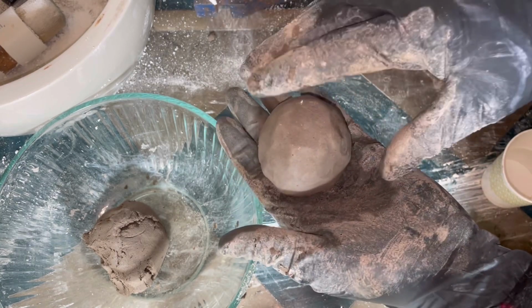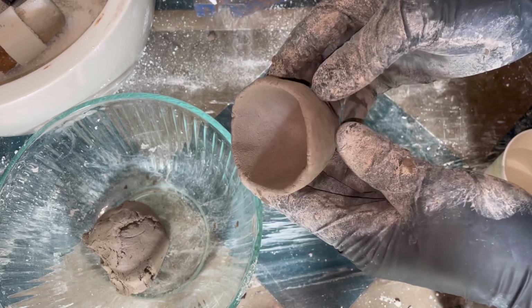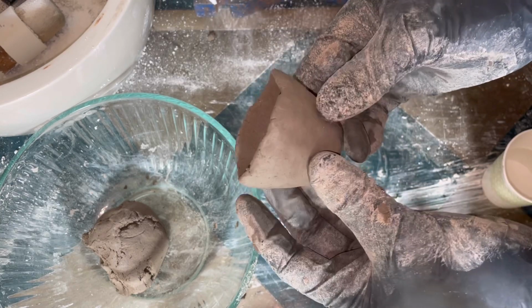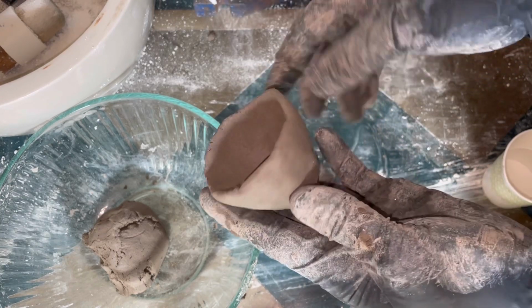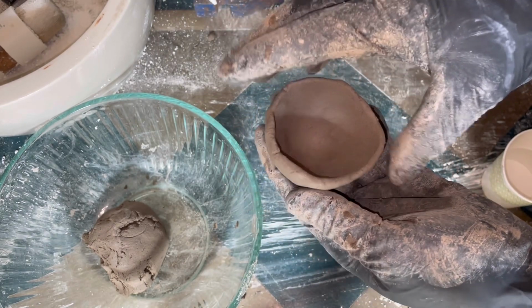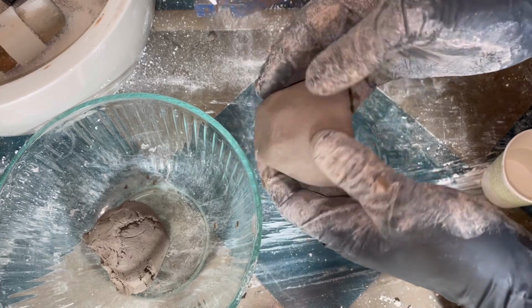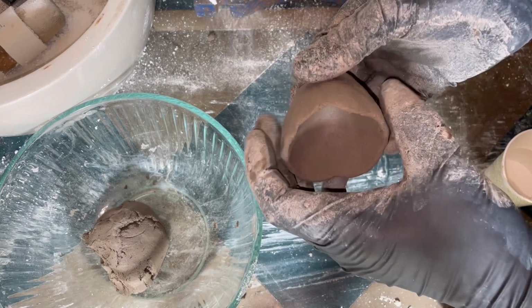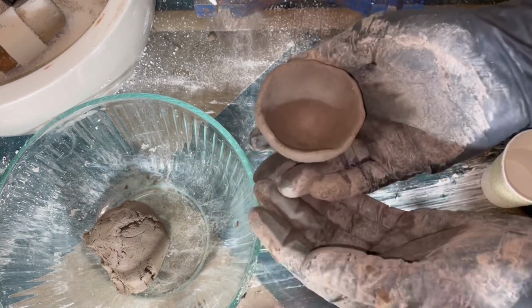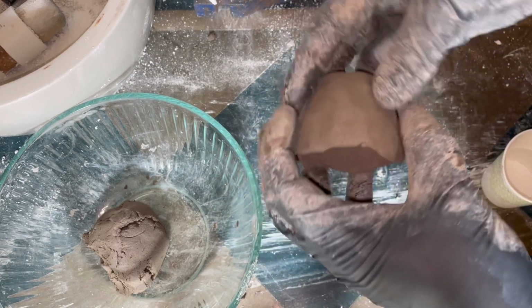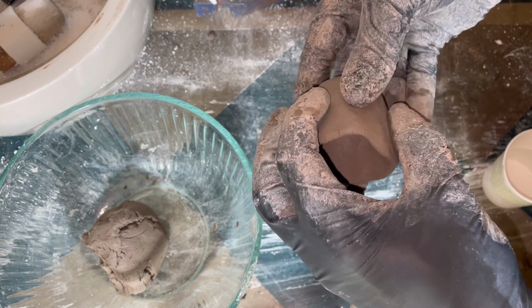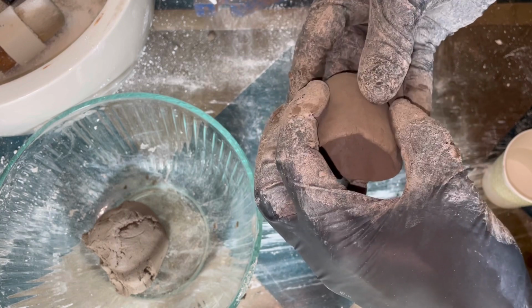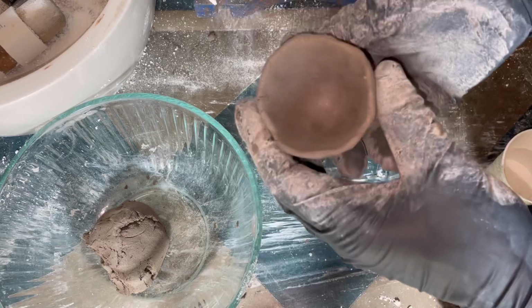Just make sure it's completely dry before you put it in the furnace. In fact, I would recommend firing it like any other form of pottery before using it as a crucible, because I'd much rather it explode in an empty furnace than with a full charge of flux. You know, if there was a little bit of moisture that built up and it did explode, that'd make a mess. There we go. Crucible.